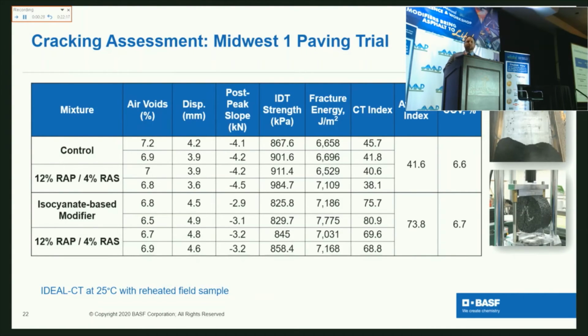Then we wanted to see what kind of cracking resistance we would get. And so the only difference between these two here is just that 1% isocyanate-based modifier. And you can see the average CT index went up significantly, just based off of those two things.